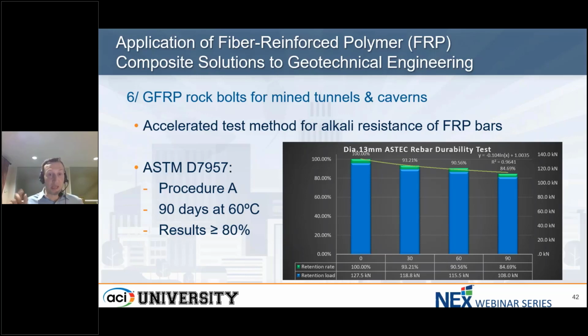And so we can just apply a factor. In ACI 440.11, the factor today is 0.85. So we discount the tensile performance by 15%, and then we get the performance of the material over time. And that's really useful for designing GFRP bolts, for example, because the alternative to that would be a steel bolt on which you have to put many corrosion mitigations, typically galvanization and/or epoxy coating and/or a corrugated pipe, all this to delay the corrosion, but always with a risk that corrosion happens.